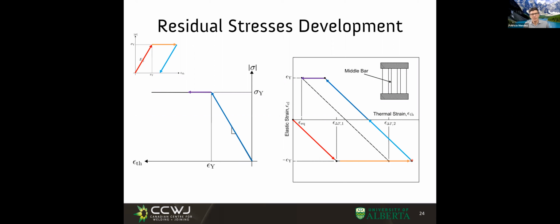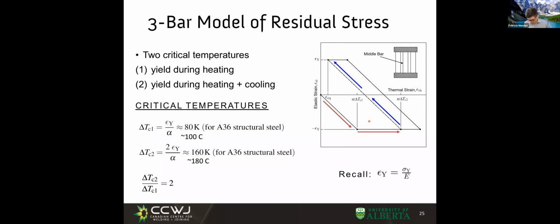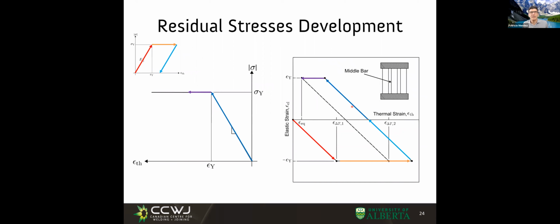And then we start to cool down after the maximum temperature, and we start to unload. But the first unload is elastic. So we are unloading all the elastic forces. It gets to a point at some temperature in which we go through no force at all, no elastic strain. And then it might still keep shrinking elastically, but now it's in tension, and it depends on the case. But when you're near the weld, this shrinkage reaches the elastic limit and starts to shrink plastically. And this is the purple part of the curve. It shrinks plastically, and the final stress at this point is going to be yield stress.